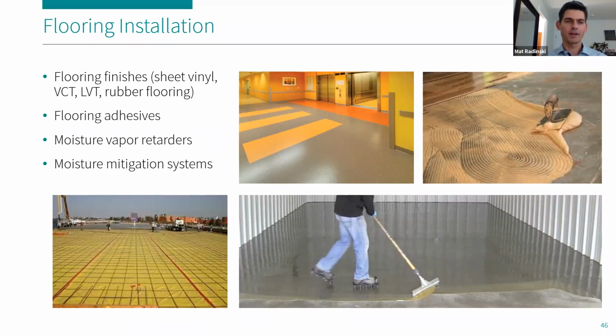As you could guess, all these products are also typically bonded to concrete with a polymeric adhesive, typically an acrylic-based or an epoxy-based adhesive. We put moisture vapor retarders, commonly referred to as visqueen, underneath the concrete slabs on grade, to minimize the risk of moisture vapor transmission through the slabs and moisture damage to moisture sensitive floorings. And more commonly, particularly in fast track, high profile construction, there's been an increased use of moisture mitigation systems, which are essentially 100% solids epoxy coatings put on brand new concrete to essentially eliminate the risk of future moisture damage to moisture sensitive floorings.